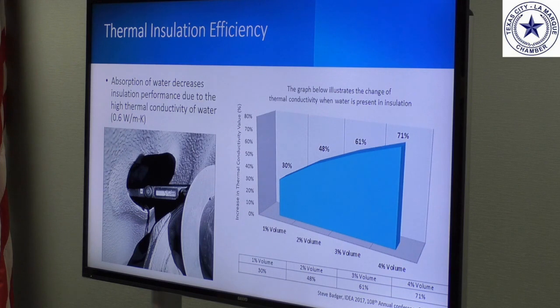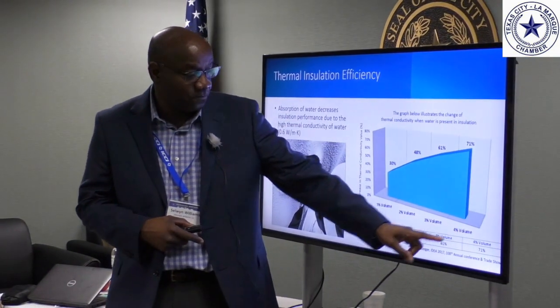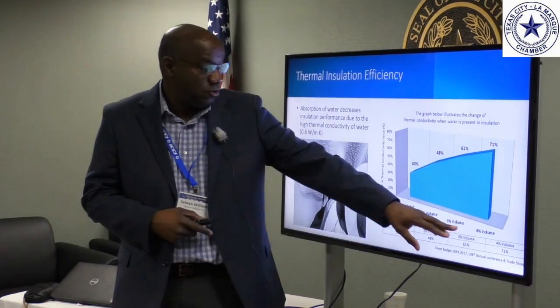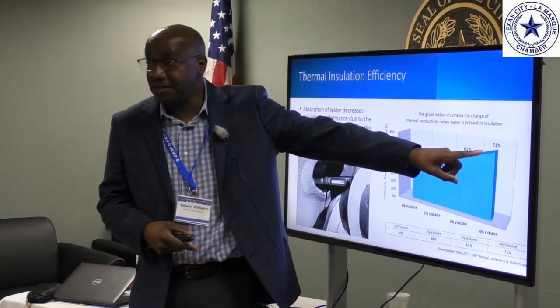Also, as mineral wool gets wet, the thermal conductivity of that mineral wool goes up. For good insulation, you want to have low thermal conductivity. So low thermal conductivity equals good thermal efficiency, and vice versa. High thermal conductivity equals low thermal efficiency. And this graph illustrates that. So you look at 4% volume of water in insulation, and you lose 71% of the thermal efficiency. So again, water is your enemy for thermal efficiency and also for CUI.